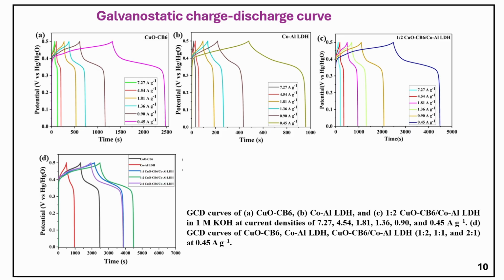The specific capacitance values were found to decrease as the current density increased. This is because electrolyte ions require more time to diffuse into the electrode's active surface region at higher current densities. The specific capacitance values of both pure cobalt aluminum LDH and CuO-CB6 are significantly lower than that of the 1:2 nanocomposite. This suggests that the deposition of CuO-CB6 on the surface of the cobalt aluminum LDH layer is crucial for improving the specific capacitance. The enhanced specific capacitance of the 1:2 nanocomposite is attributed to its improved charge transport behavior and a greater number of active sites.